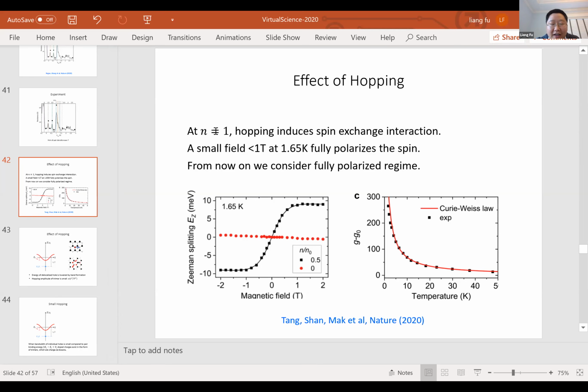So first, at filling n equal 1, the charge transfer insulating state, hopping induces spin exchange interaction. And to make my life easier, I'm going to consider an applied magnetic field so that spins are fully polarized. Okay, so this is totally different from the case of cuprate. In cuprate, the antiferromagnetic exchange interaction is very strong in the undoped case. However, in these TMD heterobilayers, experiments show that a small field less than 1 Tesla is already sufficient to fully polarize the spin. I won't discuss the details of these results. All I want to say is that from now on, I'm going to consider the fully polarized case. So the spin degrees of freedom are completely frozen. And we will see that yet something interesting still can happen in the fully spin polarized regime.